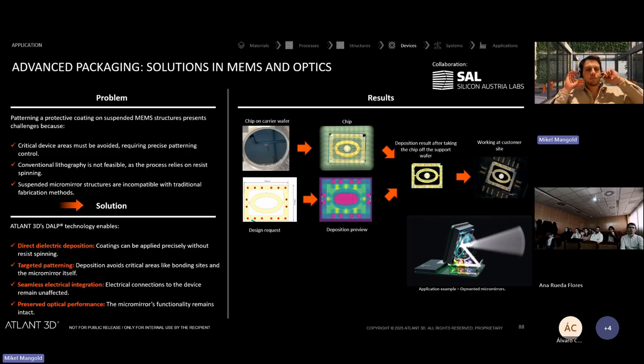And this is, I think, a protective layer. If I'm correct, it was titanium oxide, but on a fully processed MEMS device with a Bragg mirror. Usually after you make the MEMS, you cannot do anything anymore. But we were able to locally coat a protective layer on the MEMS, and we did that in a collaboration with Silicon Austria Labs. After coating it, they tested the MEMS and it was fully functional.